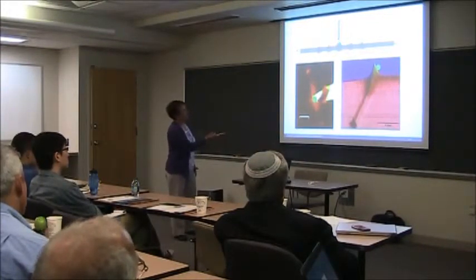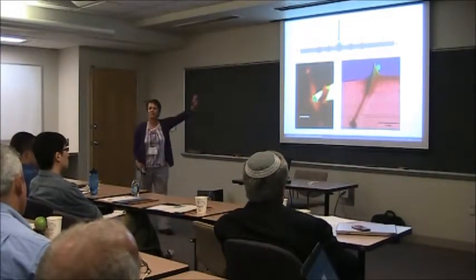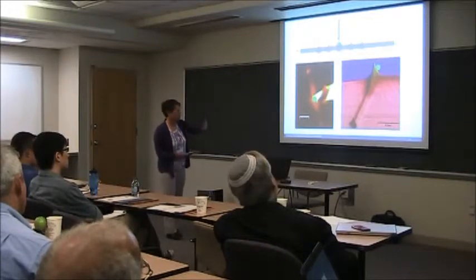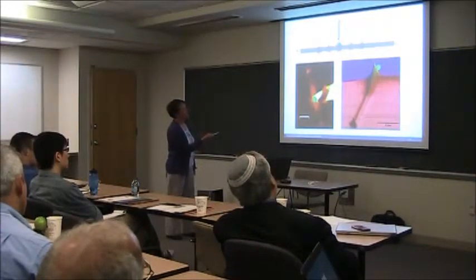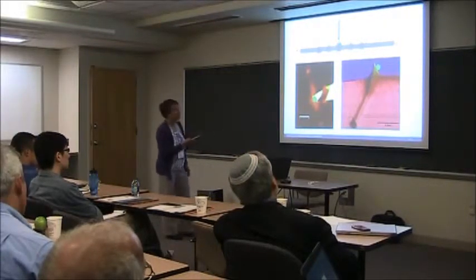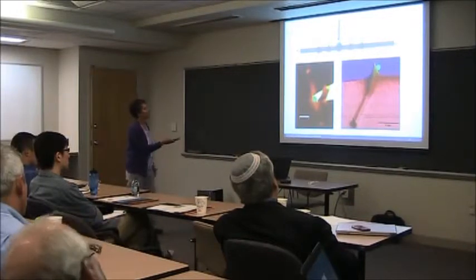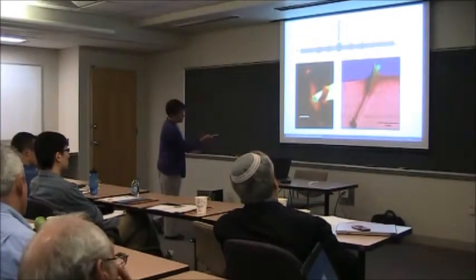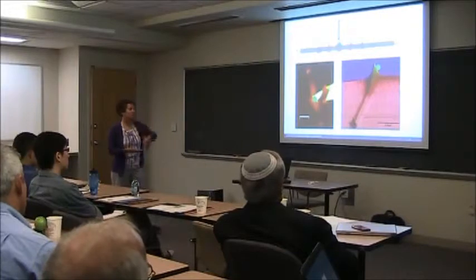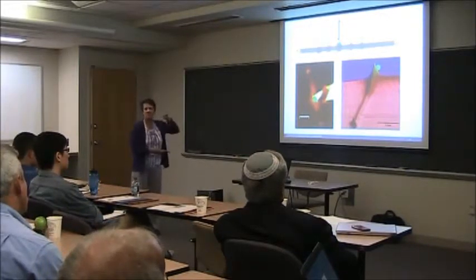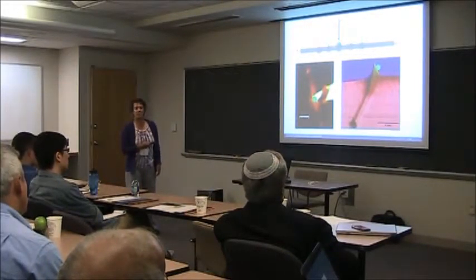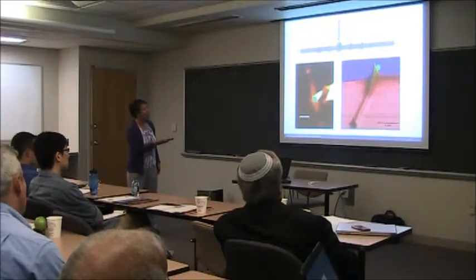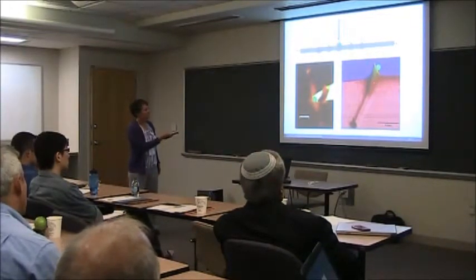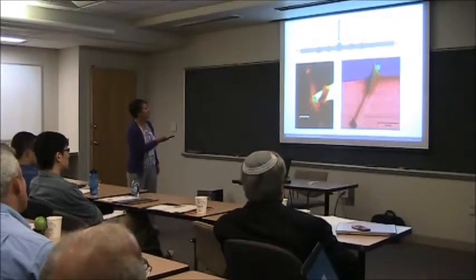So here's one image. The electron beam is at my famous green point right off the edge of the sample. So I'm off where I start to collect, and then my probe tip is going to scan here. You notice what we believe is carrier diffusion due to recombination along the way. We get a little backbone luminescence that I think is leakage out of the thing, and then you come down to the end, and there's your nanowire as waveguide. So photon transport, electron or minority carrier transport, etc.